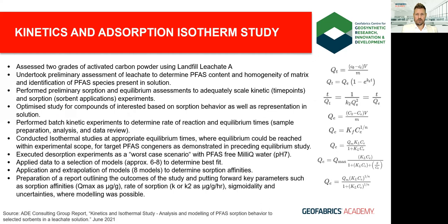With that knowledge, we selected a particular coal-based activated carbon which had already been designed by the manufacturer to assist in capturing PFAS molecules. We recently carried out a kinetics and adsorption isotherm study through ADE to quantify the performance of this activated carbon with landfill leachate, in isolation of the bentonite component. We used Leachate A as the contact liquid because it had a range of potentially fouling co-contaminants. We looked at two grades: one with around 1,300 square meters per gram specific surface area, and another with just over 1,000 square meters per gram.